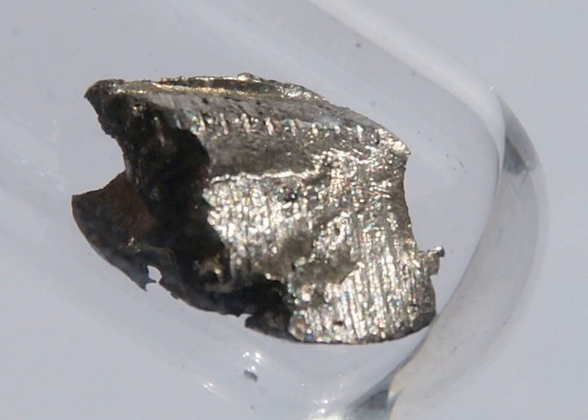Like all rare earth metals, cerium is of low to moderate toxicity. A strong reducing agent, it ignites spontaneously in air at 65 to 80 degrees Celsius. Fumes from cerium fires are toxic. Water should not be used to stop cerium fires, as cerium reacts with water to produce hydrogen gas. Workers exposed to cerium have experienced itching, sensitivity to heat, and skin lesions. Cerium is not toxic when eaten, but animals injected with large doses of cerium have died due to cardiovascular collapse. Cerium is more dangerous to aquatic organisms, on account of being damaging to cell membranes, but this is not an important risk because it is not very soluble in water.